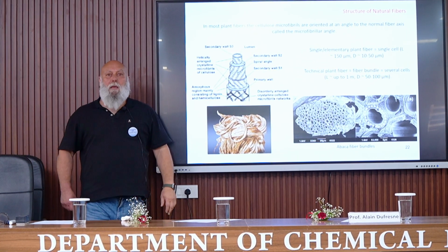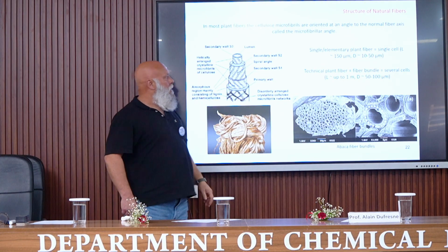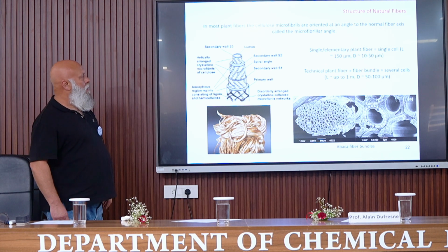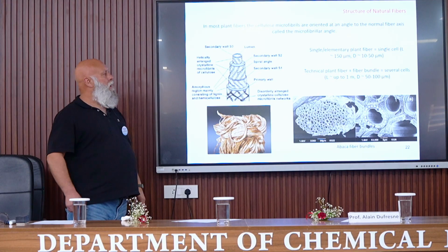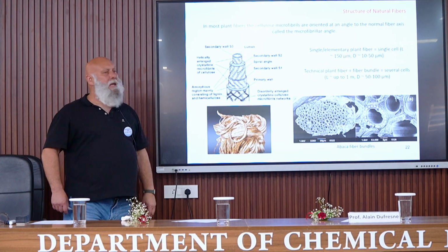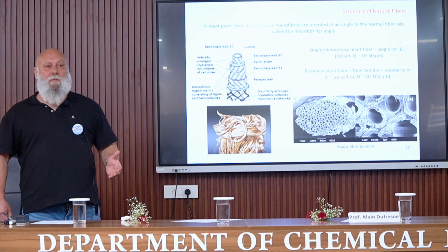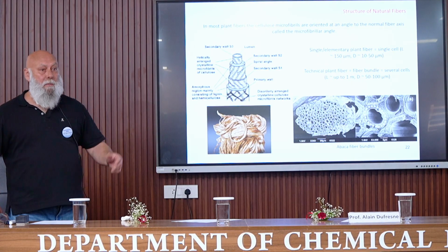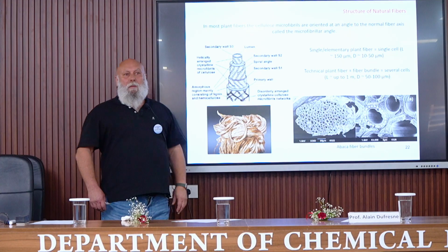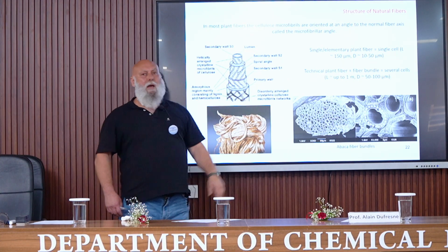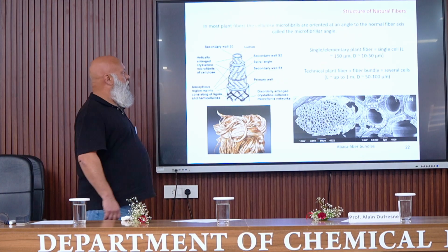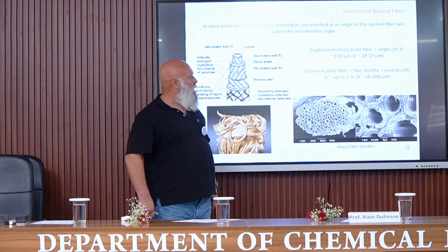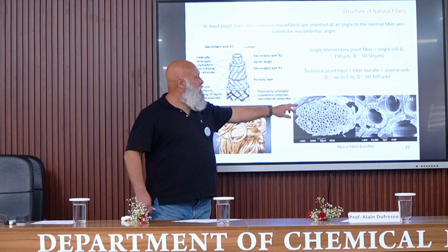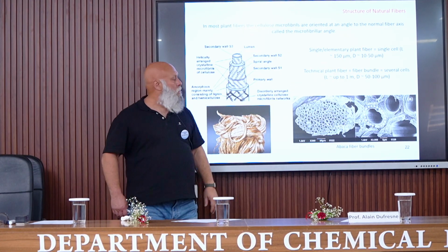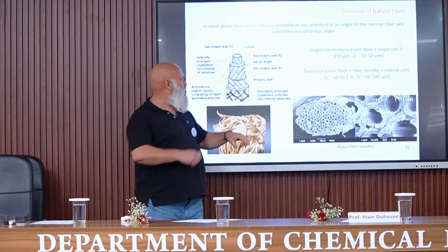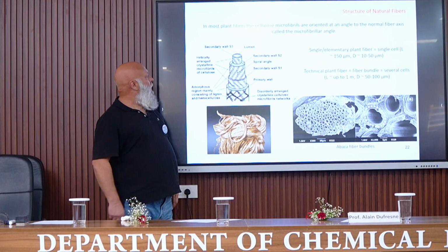So you have here the typical dimensions of natural fibers. When considering a single fiber, which is also called an elementary plant fiber, or single cell, you can see that the length is around 150 micron, and the diameter ranges from 10 to 50 micron, which is similar to what is found, for example, for glass fibers or carbon fibers. But usually in biocomposites, technical plant fibers are used. It consists of a fiber bundle, so of course the dimensions are much higher. The length can be up to 1 meter, and typically the diameter ranges from 50 to 100 micron. You can see here this technical fiber that consists of the association of many elementary fibers.